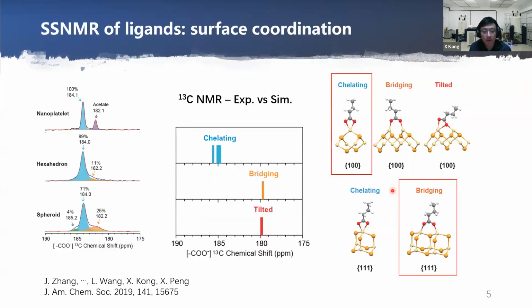In our previous works, we studied the coordination structures of the ligands on nanocrystals. This study relies on the C13 chemical shift and DFT calculation to show that different facets prefer different coordination configurations. For instance, the 100 facets prefer the chelating conformation, while the 111 facets prefer the bridging configuration.